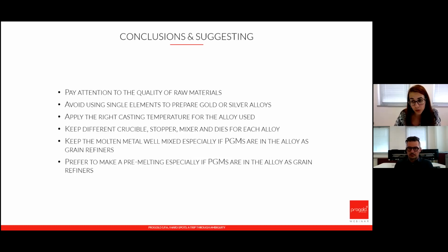Please, it's very important to use the pre-melting, especially in continuous casting, because it's very, very easy to have hard spots in such a process. And please be careful about grain refiners. They can be a very helpful thing, but if not used properly, they can also give you a lot of problems if you don't know what you're doing.